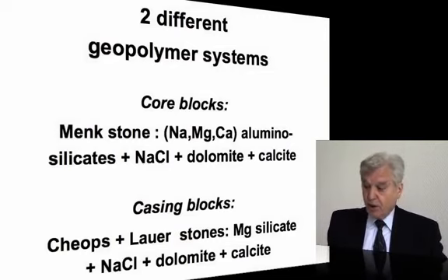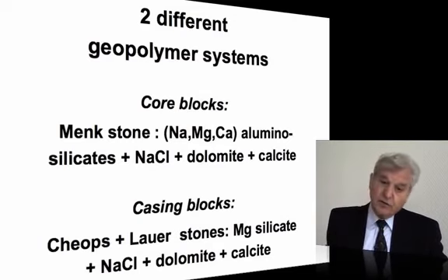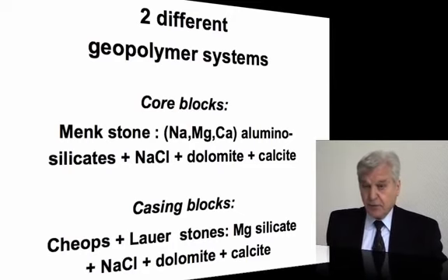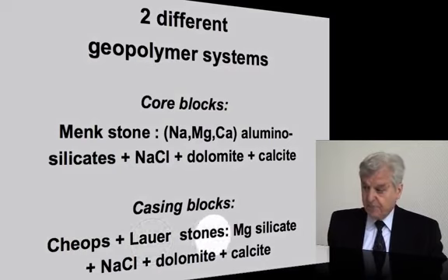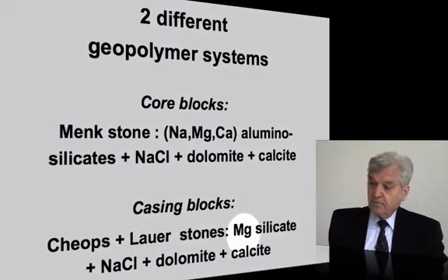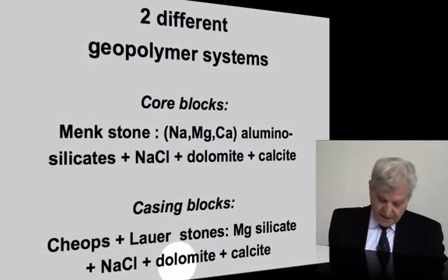And the casing blocks have up to 10% of silica in the constitution, which is a lot for the geological glue, and are represented by the samples we got from Cheops and the Lauer stone. It is magnesium silicate, sodium chloride, dolomite, and calcite.